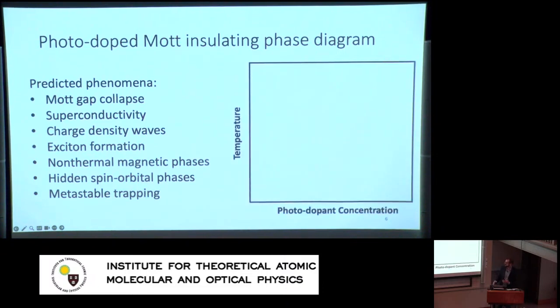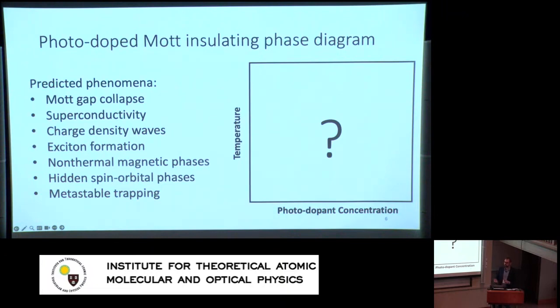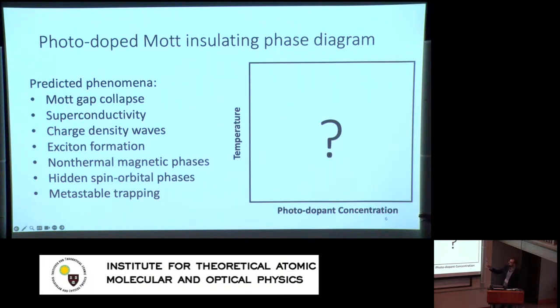You may ask, what is the phase diagram you can compile from all of these results? Unfortunately, experimentally we don't know — most of these phases haven't been observed. What we have observed so far is the onset of metallicity, and there are debates as to whether that's simply because free charges have been created or whether you're actually collapsing the band gap. The other thing we've observed is non-thermal melting of the antiferromagnetic order, where the antiferromagnetic order disappears beyond a certain threshold of doping, similar to equilibrium. But we haven't seen the emergence of any other of these phases.